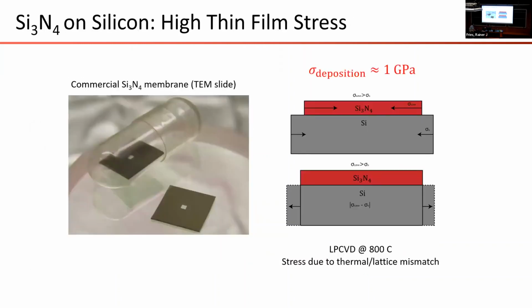At the nano domain, you can actually get very similar stresses, but much bigger aspect ratios. The standard way to get high stress, for example, is via thermal mismatch. Silicon nitride on silicon is a very standard thing to do in the silicon industry if you want to controllably strain silicon. That's useful, for example, for engineering the electrical transport properties of silicon transistors. So people know very well how to deposit strained materials on top of silicon. So standard LPCVD silicon nitride ends up with 1 gigapascal stress just due to thermal mismatch, for example.